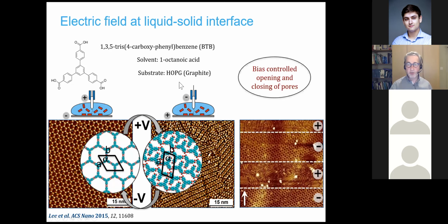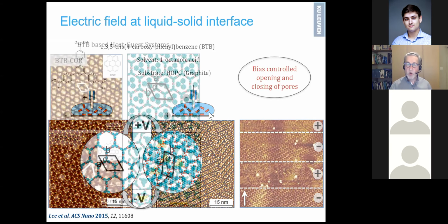Now, what about functionality? Well, you could consider this as a responsive system where you can open and close the pores of such a monolayer, one molecule thin network at the liquid-solid interface. And indeed, by changing the bias, we can go from a high density, so non-porous, to porous network, high density, and porous network. Of course, limited functionality so far, but it becomes more interesting when we consider that